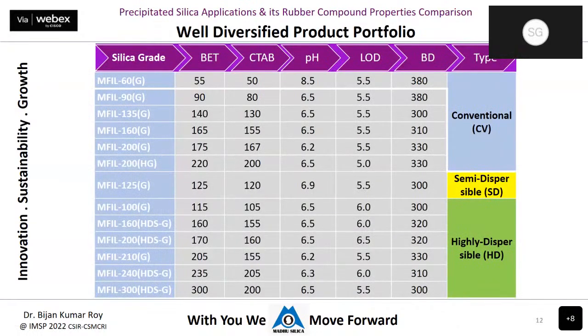Now we are representing Madhu Silica. Madhu Silica has a well diversified product portfolio. If you look at this product table, you can see that we have different grades of silica, starting from a surface area as low as 50, 55 to as high as 300 square meters per gram. So based on this surface area, we classify different grades of silica, which give different product properties to a particular tire compound.